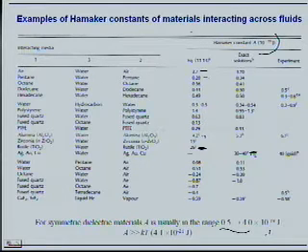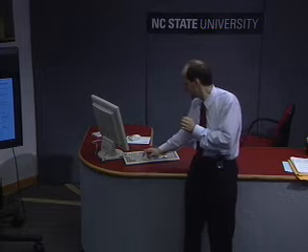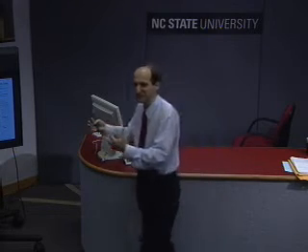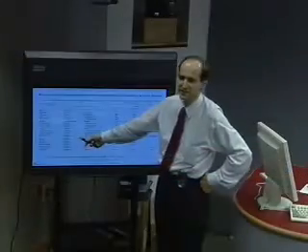It's an order of magnitude larger than anything that you can see, with the exception of some solid bodies. The reason for this is that metals have very high polarizability. So now let's say we have given some answer to why metal particles would stick to each other in water. Their interaction is an order of magnitude larger than other particles. And then we move on here where we have asymmetrical systems.